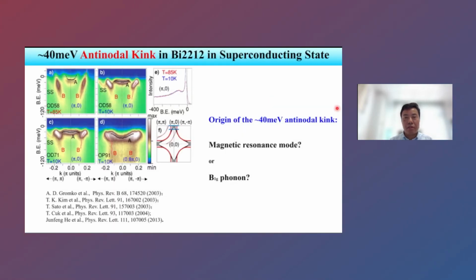Also, there's another kink called the antinodal kink, near the antinodal region. But this kink is observed only in Bi2212 in the superconducting state. So only in this material, only in the superconducting state near the (pi, 0) antinodal region, there is a kink called the 40 millielectronvolt antinodal kink. But it is also still under debate whether this kink is due to phonon or due to magnetic mode.